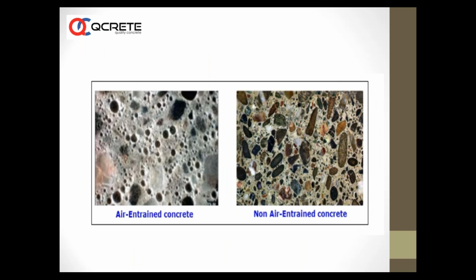You can see the uniform spreading of air bubbles in the body of concrete, and you can see this even after say 20 years or 30 years. If you cut a core of the concrete, you can see air bubbles after 20 years or 30 years. Some amount of air will be lost - this air will be lost during transportation. Entrained air will be lost during transportation or placement, during compaction.